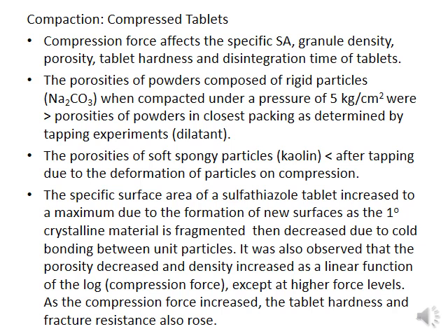These powders were dilatant, that is, they showed unexpected expansion rather than contraction under the influence of stress. In the case of soft and spongy particles, such as kaolin, the particles deformed on compression and the porosities were lower than after tapping the powder down to its condition of closest packing.